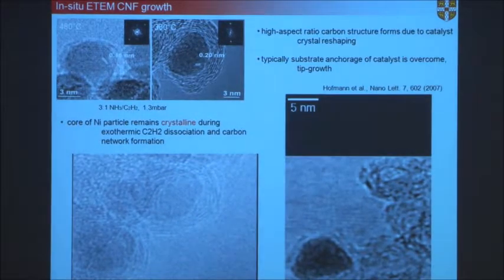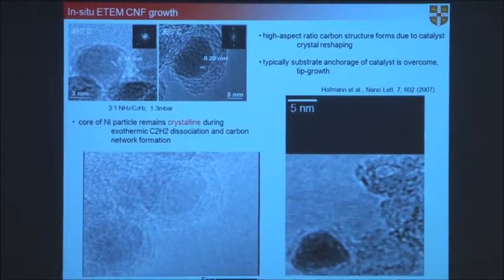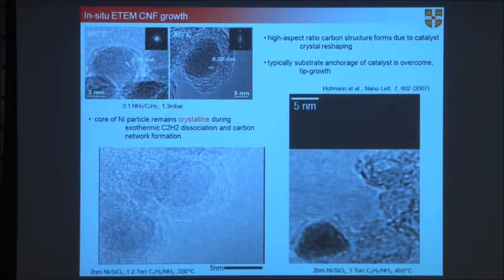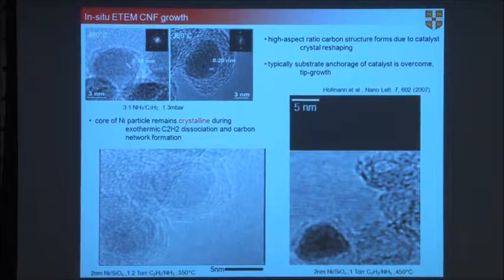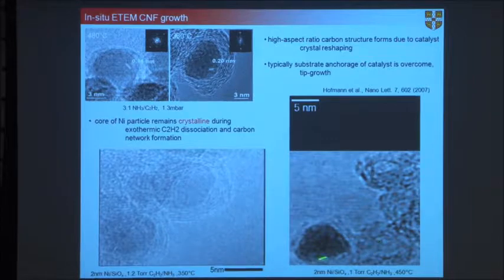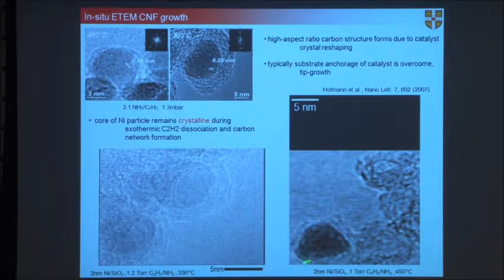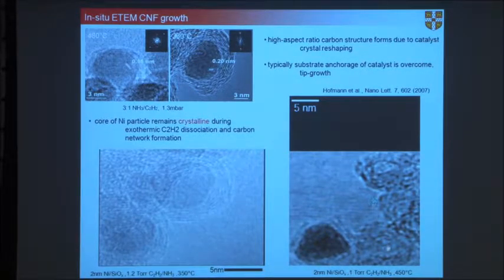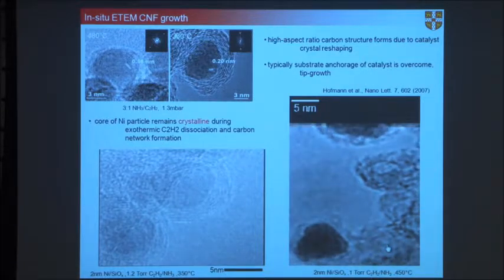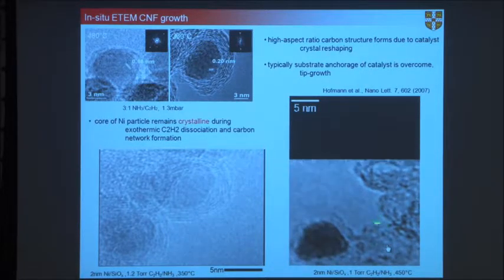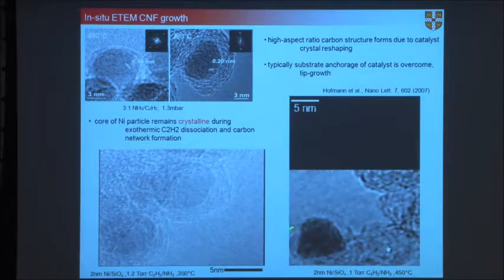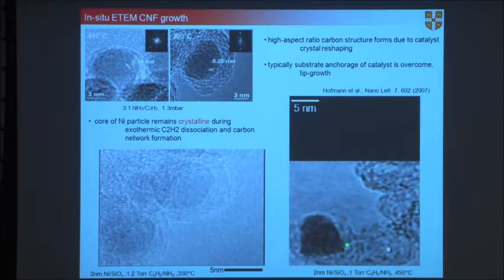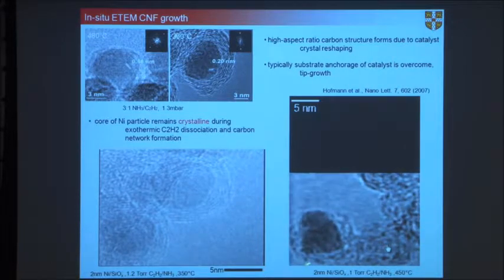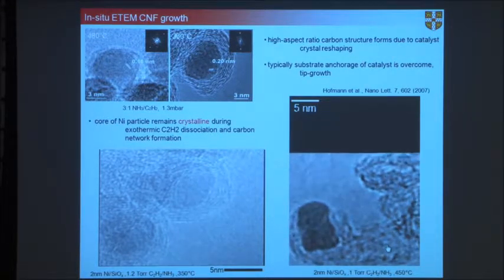And just to give you some in situ, one of my colleagues, Stephan Hofmann, did some in situ growth studies of carbon nanotubes. And what he did here was to look at a nickel dot, this is a nickel catalyst, on an SiO2 substrate on silicon. So it's silicon, SiO2, and then nickel, and just see what happens, hopefully, if the movie works. Yep. So what you'll see is when the nickel dot's this big, the carbon starts coming in here, it starts going down the side, pushes down the side, and eventually you'll see it pushes the nickel catalyst off the substrate, and that gives you an example of a tip-growth process.